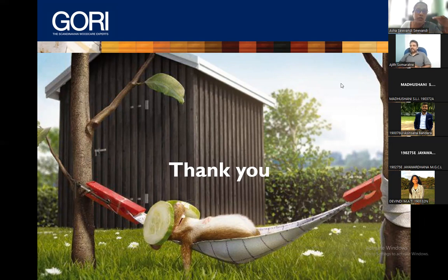One thing I have observed with some water-based products: sometimes when they interact with water, the water becomes colored with some kind of dye. It is actually because of a failure of the product. Sometimes in some products they use a dye coat first and then a top coating. This dye coating is just a color, and sometimes it is soluble in water. So it is actually a defect of the product, not because it's a water-based product.